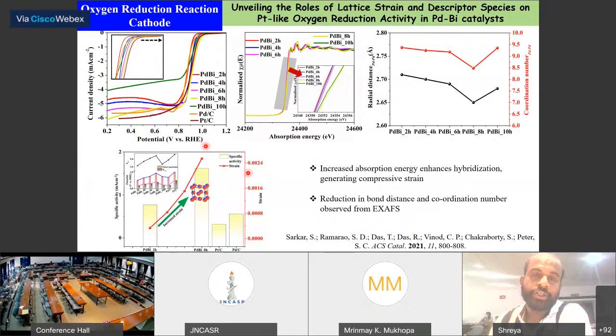That can end up in an average coordination environment that is much less in the case of smaller nanoparticles. We also found that the increased absorption energy enhances hybridization, generating a compressive strain. You can see the radial distances calculated from the EXAFS fitting at different milling times, and at 8 hours milling time there is a drop in the radial distances and the coordination number that induces a strain within the system that enhances the activity. As you see, the specific activity is highest for the 8 hour sample.